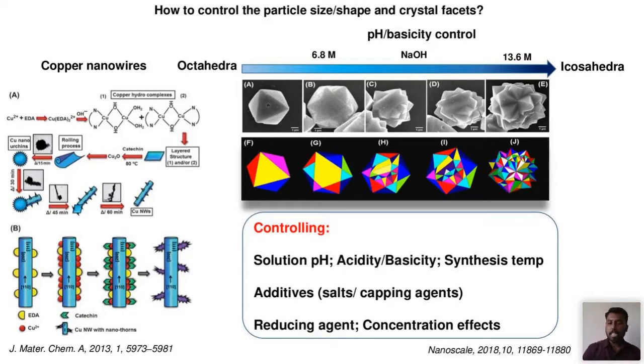So a capping agent is a substance which will cover a metal ion when it is nucleating, and it will suppress the growth of the particular particle in one direction. For instance, if you want to grow a nanowire in 111 direction, then you can use a particular capping agent. If you want to grow an octahedra shape or cube shape, then you can go for a different capping agent. So by selecting different capping agents, you can control the growth of the nanomaterial and reducing agent concentration.